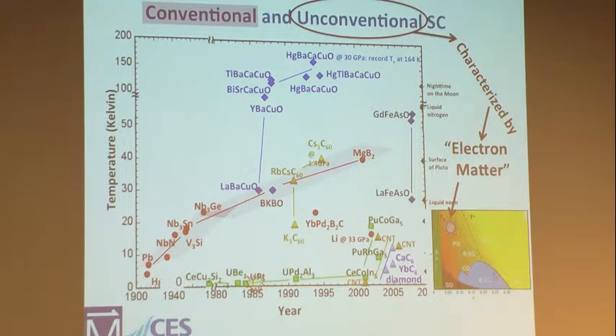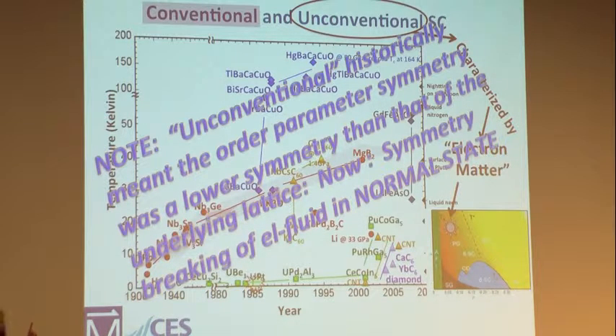So here's my definition, conventional and unconventional, okay? So all conventional superconductors are the red ones on here, and all the unconventional are off of this, and they all have this kind of phase diagram, and they all have this electron matter up here. Okay? This is different than the definition a few years ago. The definition a few years ago was based on the superconducting order parameter, which is the wave function that you square to get the gap. So you have some wave function, and you can write down that equation. If the symmetry of the superconducting order parameter is lower than that of the underlying lattice, D-wave where you have plus and minus as opposed to S-wave, that's a lower symmetry than a tetragonal lattice. So that was considered unconventional.